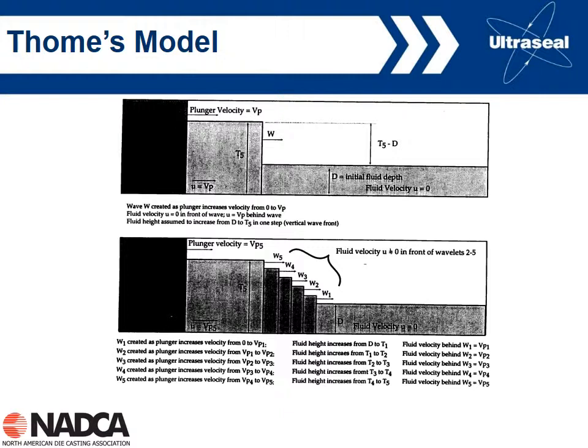So the lower diagram shows Thome's concept, and what she said is that we should use this accelerating slow shot velocity. So instead of producing one single wave, we're creating a series of smaller waves. It becomes easy to control. As you can see here, the severity of the wave is much less. It's much less likely to break, and this is especially true for the low fill ratios, fill percent in the sleeve.